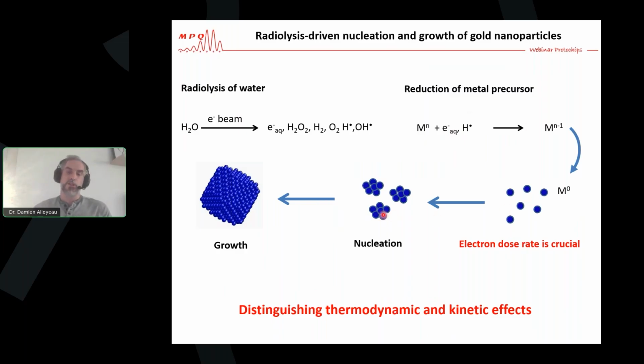But what is very interesting is that the electron dose rate allows controlling the concentration of reducing agent. So now we have a way to control the kinetics of the reactions and the thermodynamics of the environment by controlling its composition. So we have a great tool to distinguish between thermodynamic and kinetic effects.